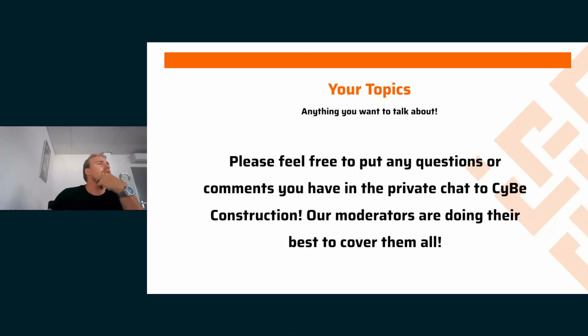In case of unforeseen circumstances like rains, flooding, cyclones during construction process, how do you manage it? We try to keep an eye on the weather app. If there's heavy rains coming and we know when and we know how long the print will take, and we see that there's enough buffer, we will do the print and then go inside. If the print has been done for more than, let's say, 10-15 minutes, then it's quite capable to keep up to heavy rain because the material is hard enough.